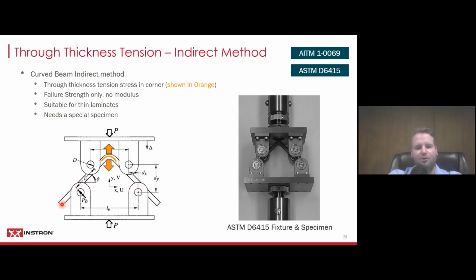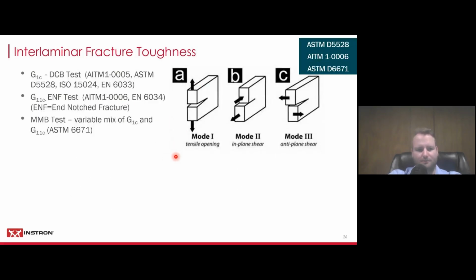So you put your specimen through, and there are the support rollers here on the bottom. You have the loading noses coming down here, which, like you can see here, gives the force application on the top and on the bottom, which then gives you a tension stress right up here in the curve of the specimen. But again, it's not possible to determine the modulus with this.